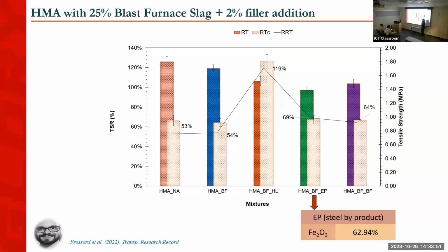We also tried to use a powder from the steel industry that was rich in iron. And this powder also seems a good alternative to improve moisture damage resistance. And we also added BF slag to see if that could enhance it. We got a little bit of enhancement by just adding BF slag on the surface.